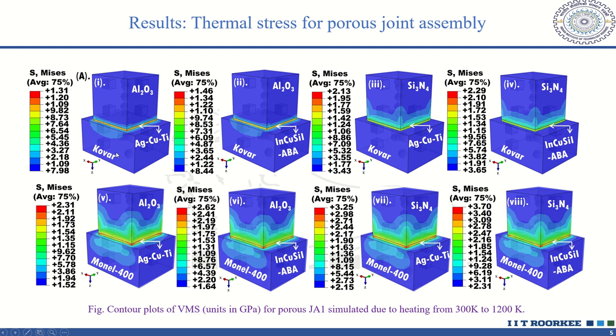The results for the porous joint assembly, that is the joint assembly design containing pores, conclude that the distribution of the von Mises stress is same as that of non-porous, that is increasing from left to right and top to bottom. However, this maximum value is lower than the non-porous joint assembly. This is because earlier there were no pores and the assembly was solid. Now, due to the presence of pores, the stress is redistributing, and so the overall stress bearing capacity of the joint assembly is